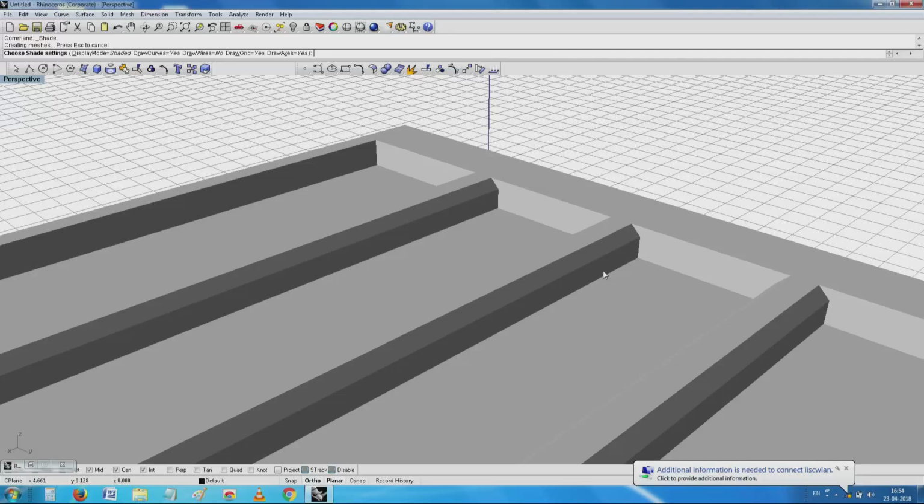The bottom first layer was the base. Depending on the thickness, suppose it is a 1 mm thickness and the resolution is around 0.2 mm, usually they will have 5 to 6 runs to build up that 1 mm, and then later on they will build the ribs. Starting from the ribs onwards, the algorithm which is used for moving the nozzle, in a very general and abstract way, the path which the nozzle takes will be different.